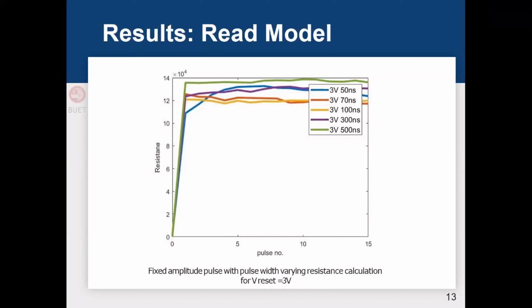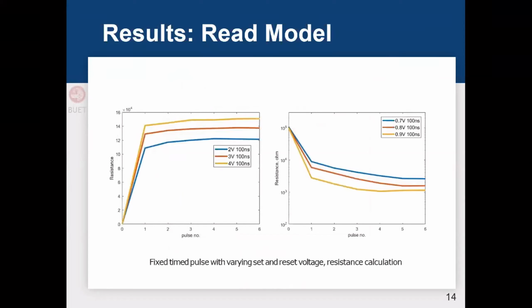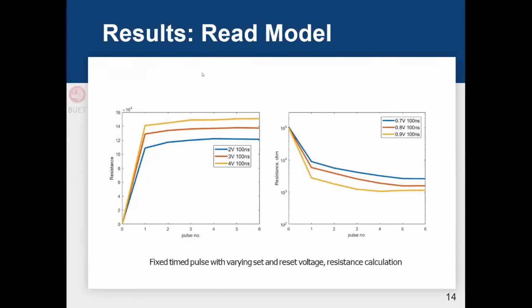And this is the same finding that we got using different types of pulsing schemes. For example, in the next slide, we can see that we have applied different reset voltages like 2 volt, 3 volt, or 4 volt with the same pulse widths. And we can see that with the variation of the pulse width, or with the variation of the voltage amplitude, or with the variation of both, we can actually settle down to different resistance levels.